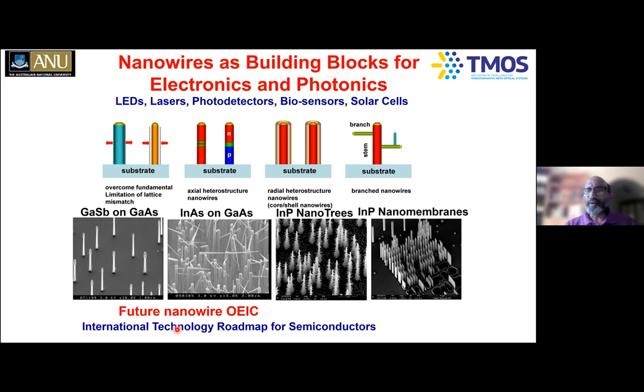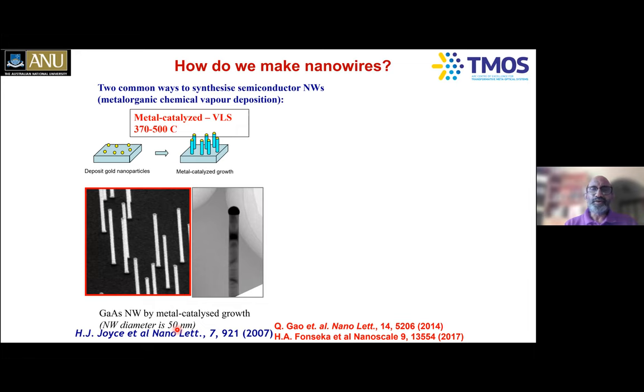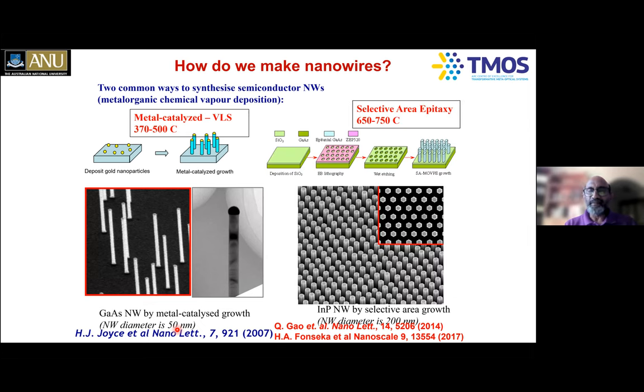If these nanowires are so much of importance, how do we make them? There are two main techniques which we use. One is called the metal catalyzed VLS growth process, where what we do is that we take some semiconductor substrate. For example, I'm giving an example of a gallium arsenide substrate. We put these nanoparticles, a colloidal solution of nanoparticles of gold, which you can commercially buy from 5 nanometers up to 300 nanometers in diameter. We put a droplet of this, say, for example, 50 nanometer gold nanoparticles on top of this gallium arsenide substrate.